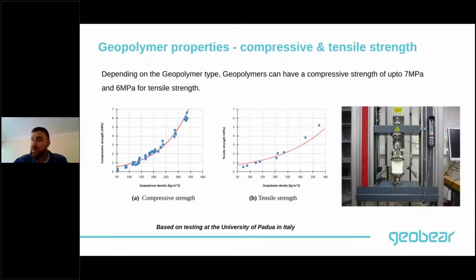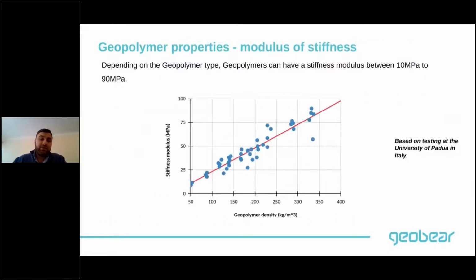Geopolymers also, depending again on the type of geopolymers, have good structural properties. So geopolymers can have a compressive strength up to 7 MPa and a tensile strength of up to 6 MPa. As you may notice from these measurements, geopolymers are kind of good in both compression and tension. So they're unlike concrete or grout. Concrete is really good at compression, but quite weak in tension. But geopolymers are good in both of these aspects.